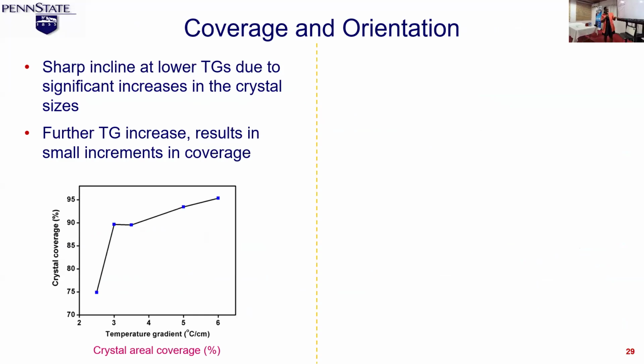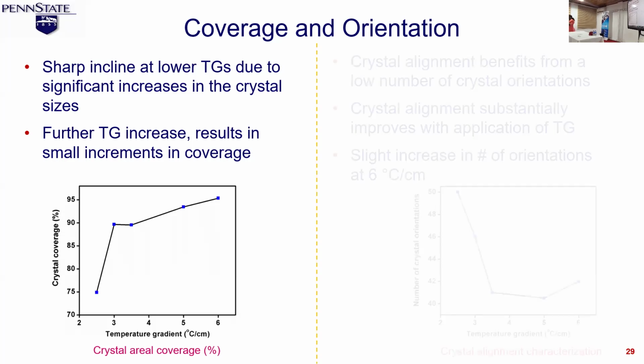So the image on the left is just showing the area coverage for the different temperature gradients. On the x-axis, again, our temperature gradient increases. On the y-axis is the area coverage. As the temperature gradient increases, our area coverage essentially increases. It gets to the point where this looks a little flat, and the increase is not as steep. And the reason why is at some point the crystals would already have bridged each other. So then your increase is only incremental.